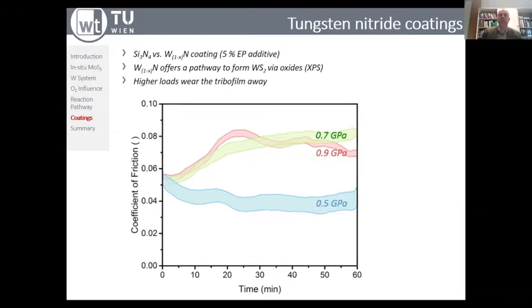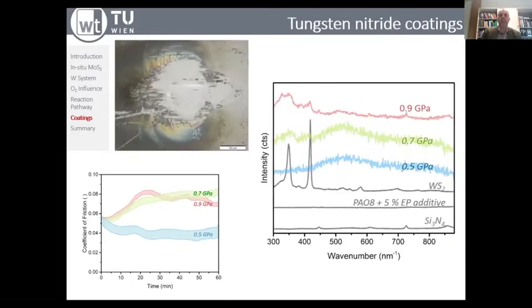But if you look in more detail at what is happening to the surfaces, this is a sketch from the ball surface, from the counter surface. And again, you can find on the right-hand side the Raman spectra for the different scenarios, for the different contact pressures. So you can detect, also for the 0.9 gigapascal, the characteristic peaks of the tungsten disulfide in the system. We also can see that around the rim on this ball surface here, there's a lot of debris coming from the tribofilm that is moved away, that is replenished again, reformed again. But even if you have a higher friction coefficient and a high contact pressure, of course, you're still forming the tungsten disulfide.